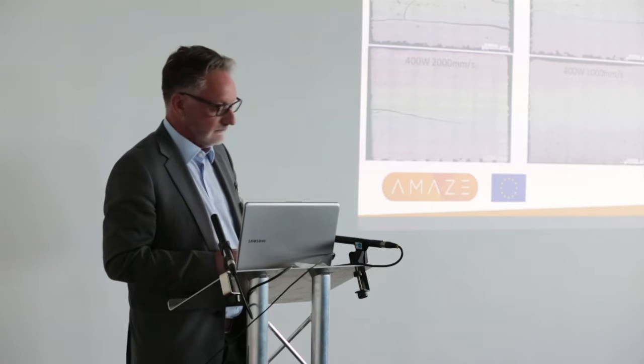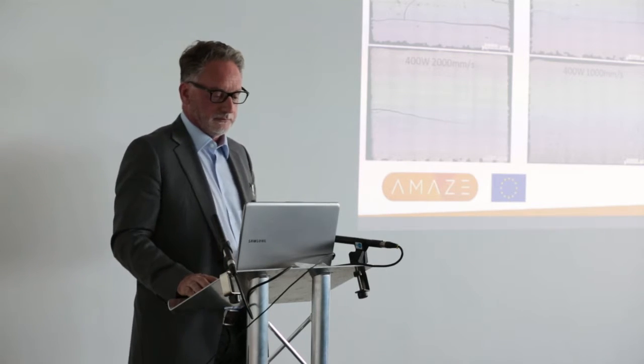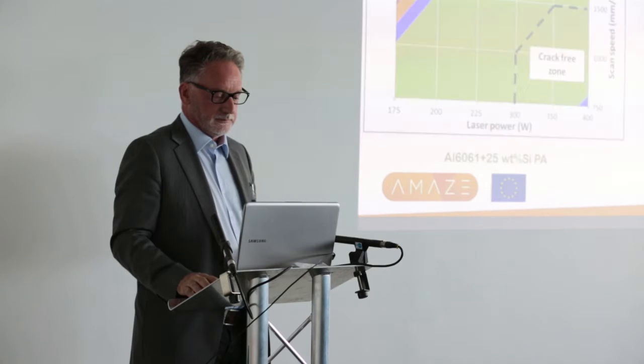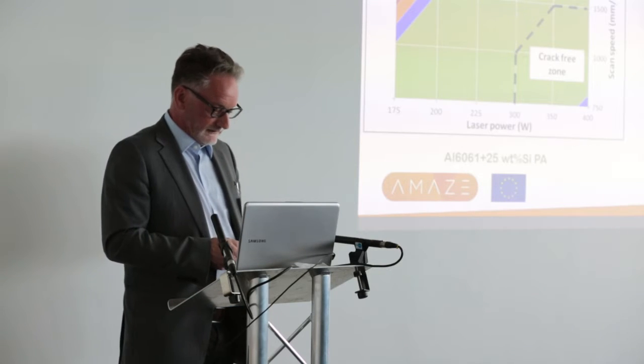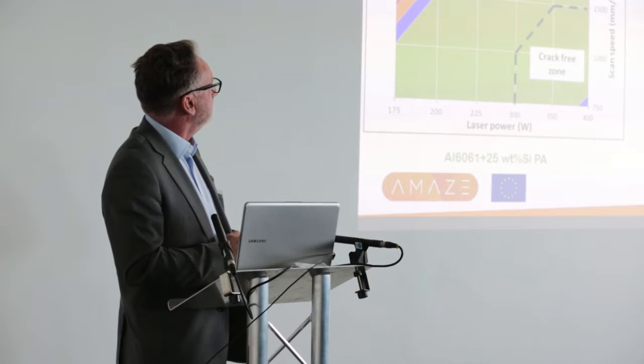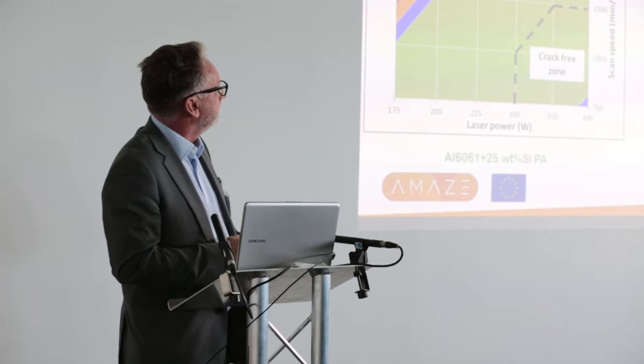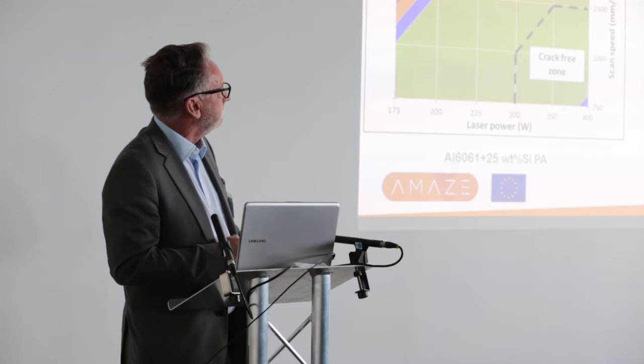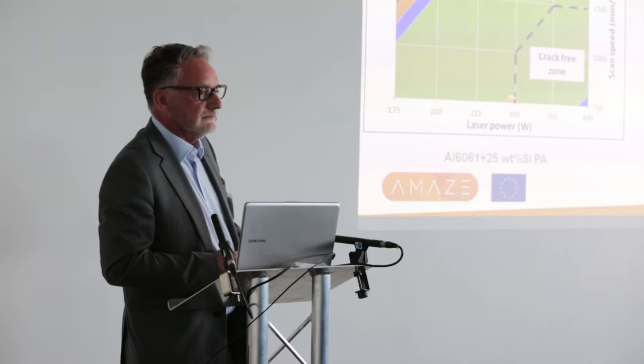This is in the 6061 material, which was more difficult to process. In the end, we had a process map, and you can see it here. All this area in the green was processing conditions where we could get high density, so above 99%, but only in this corner would we get crack-free samples.